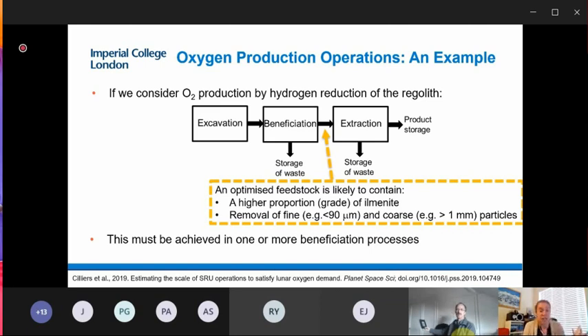And that's beneficiation. This is mineral processing. So we would like to increase the proportion of ilmenite. We would also perhaps think about removing the coarse particles and the very fine particles. Coarse particles might cause a problem with blocking. Fine particles, perhaps we might find issues with dust and sintering in the reactor. So we could start to see how the beneficiation process might be useful in oxygen production.